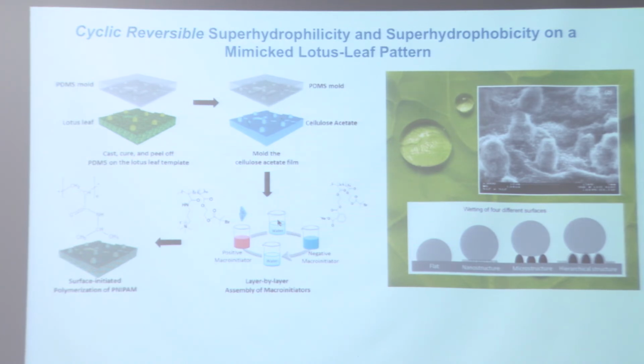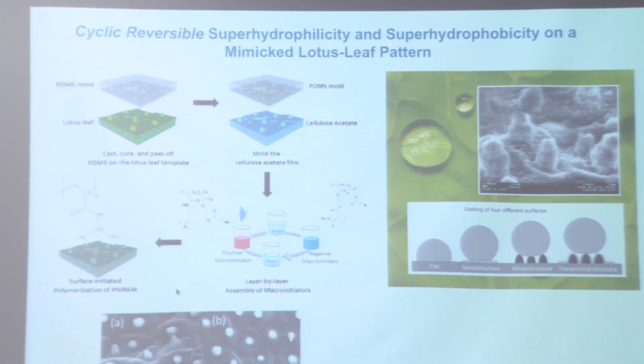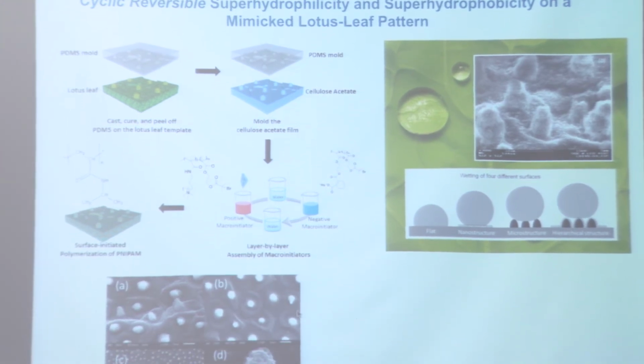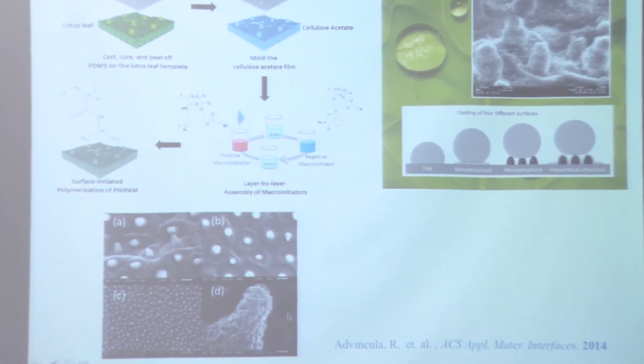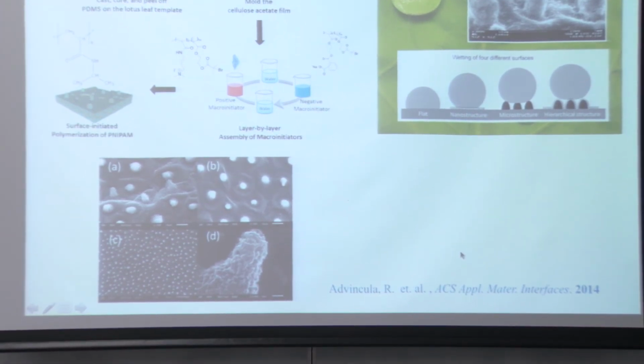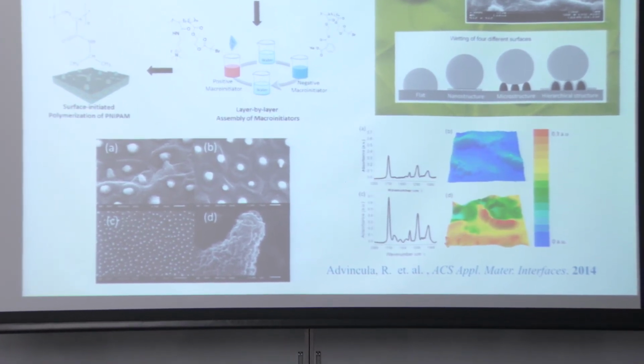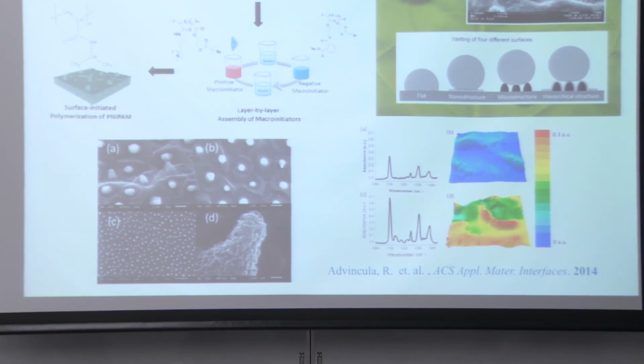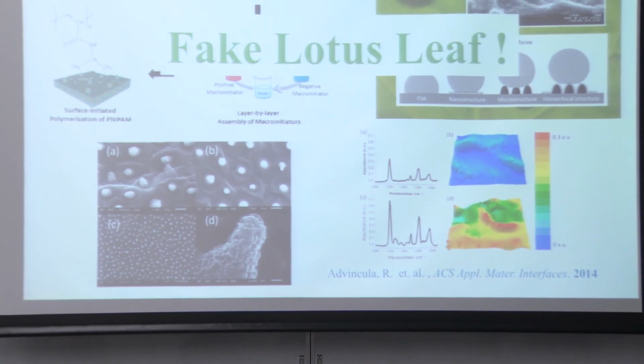ATRP, which I'll explain later, is a way of making polymer brushes. So we grafted a polymer brush of polyNIPAM, which coats the artificial lotus leaf made from cellulose acetate. Here's how it looks: the original lotus leaf and then the fake lotus leaf, with the polymer brush visible. We then used IR imaging to verify the material—this is our way of making a fake lotus leaf.